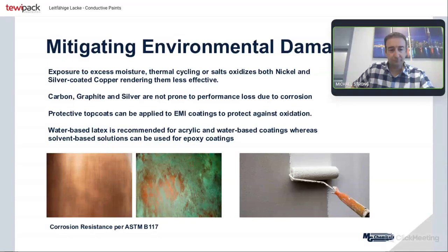On the left, we're showing you a control sample from the ASTM B117 standard. For those of you that are familiar, this is a test standard for salt spray resistance. And it's not standardized in terms of any pass-fail result or time in which you immerse your samples. The customer can decide that. So we typically run these for a week, and we'll look at any weight gain, which you attribute to corrosive salt, but we'll also measure the conductivity before and after to judge how well it does, in fact, in the ASTM standard.